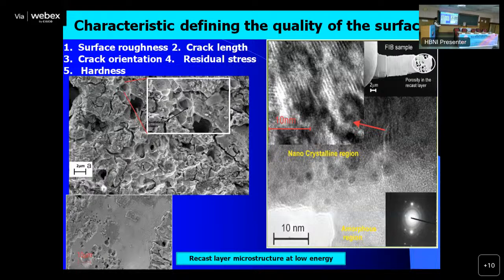And we found that the top layer, when we did electron microscopy, is amorphous. Local glass has formed. That would mean that it's not only melted, it has cooled very fast to get you a glass, amorphous layer. So you have an amorphous layer on top, and that will have a different property compared to the base. This is with high energy input. With the low energy, you can see the change in the surface. Very smooth. So normally one would not do studies like this. We have done these studies and shown how change in the energy can lead to change in the appearance of the surface by doing extensive studies. So it will tell you not only how to change the energy for getting better surface, this will also tell you how to keep the microstructure not so much different from the base. If the microstructure is very different, then your surface will behave totally differently from the base, and that you don't want.